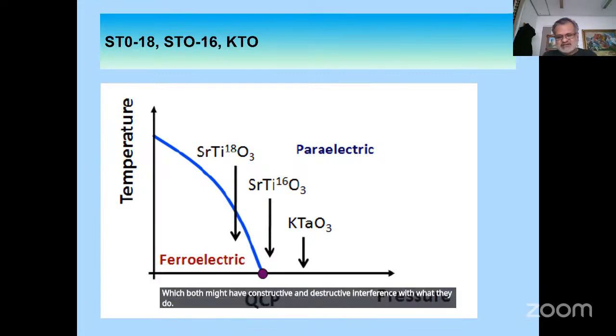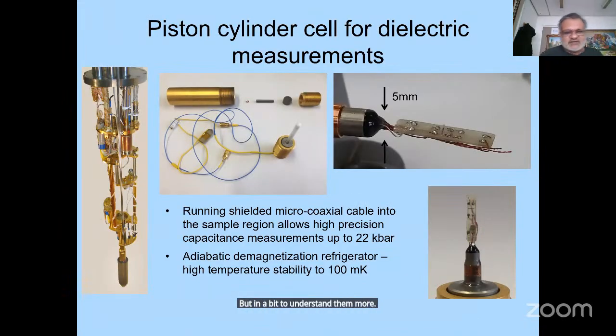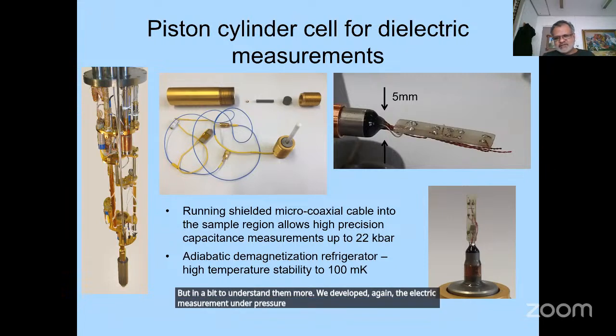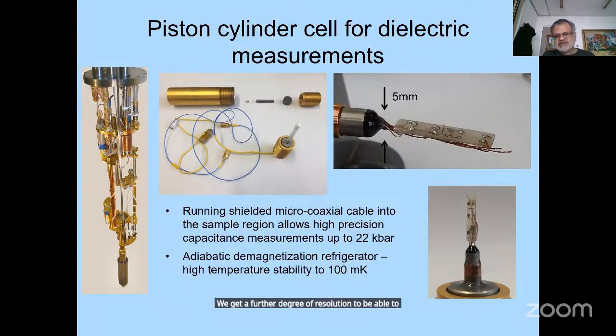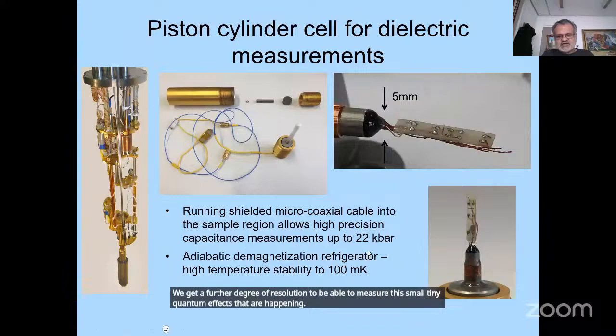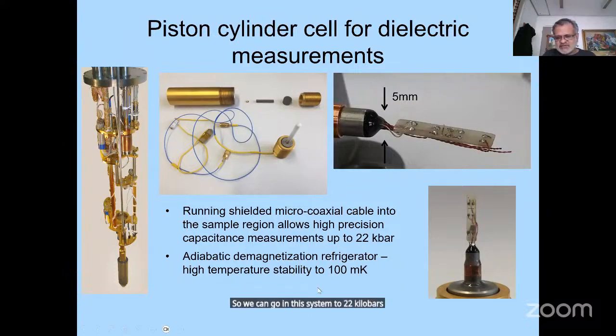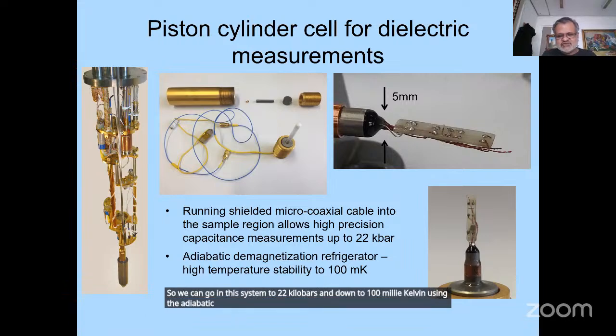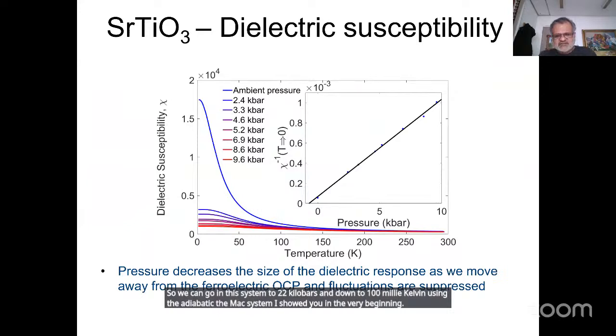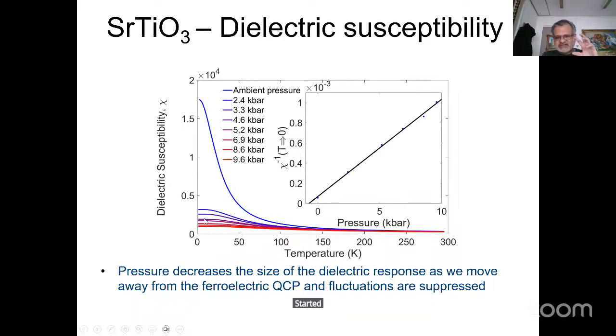But in a bid to understand them more, we developed dielectric measurement under pressure, and this is one of the few places where we can actually take the coaxial cable into the pressure cell. Most people measure outside, so we get a further degree of resolution to measure these tiny quantum effects. In this system we can go to 22 kilobars and down to about 100 millikelvin using the adiabatic demagnetization system I showed you in the very beginning. These are known results, others have shown them, but you can see how dramatic it is: with just a tiny pressure, 2 kilobars, you start to tune this quantum paraelectric state quite heavily.